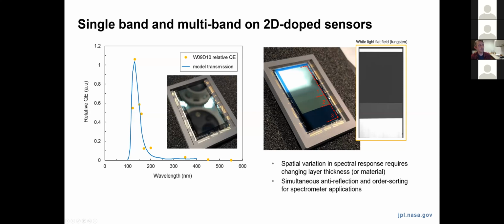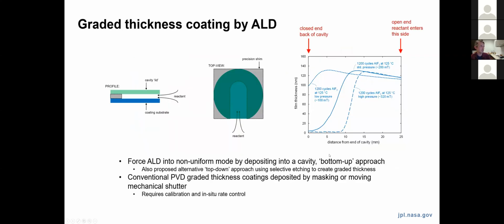So you might have imaging applications that could benefit from large format detectors with different coatings on different areas of the device. Or for spectroscopy applications, ideally you could tailor your coating to re-optimize the coating performance to match the dispersion of light that you're getting in your spectrograph system. And so that requires essentially changing the thickness of these materials, or maybe even changing the material itself as a function of position. For a lot of spectroscopy applications, what you really want is a continuous grading in the coating thickness.